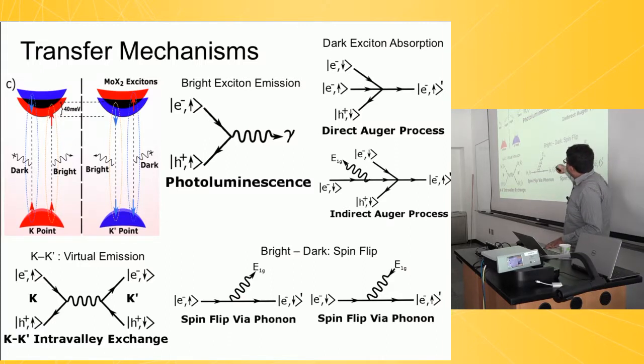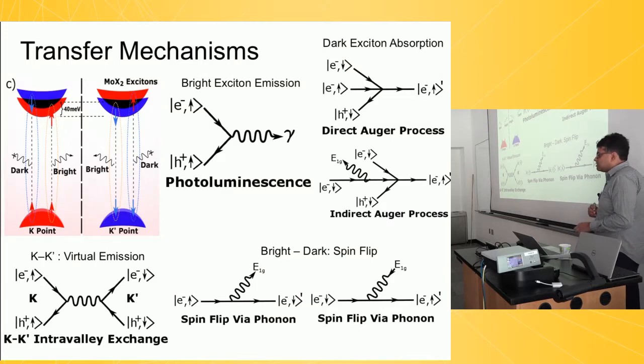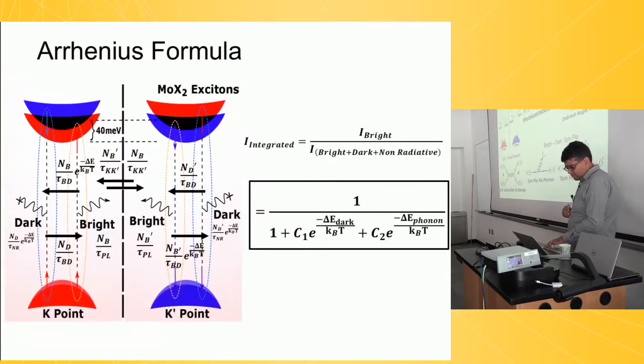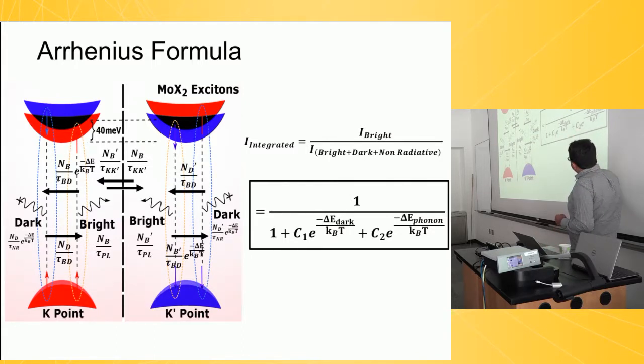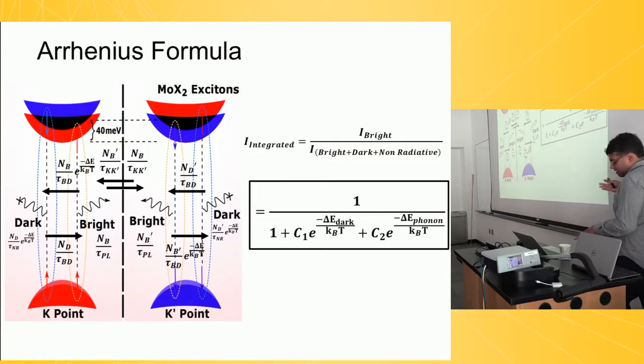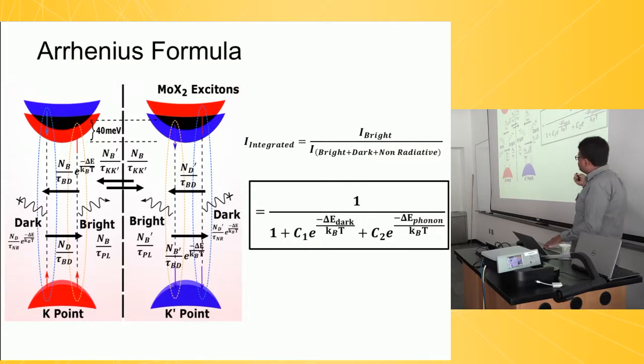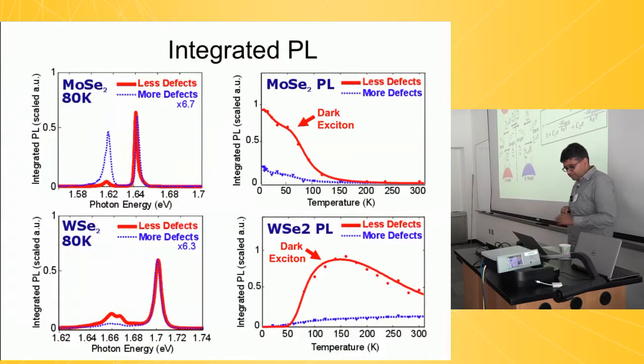So we expect that the temperature dependence of the photoluminescence when I look at a clean crystal and when I look at a dirty crystal are going to be quite different from each other. And we wrote down a simple phenomenological model. I won't go into this. We just wrote down some transfer rates from going from one valley to the other, and came up with some simple formula that we could fit our data to.